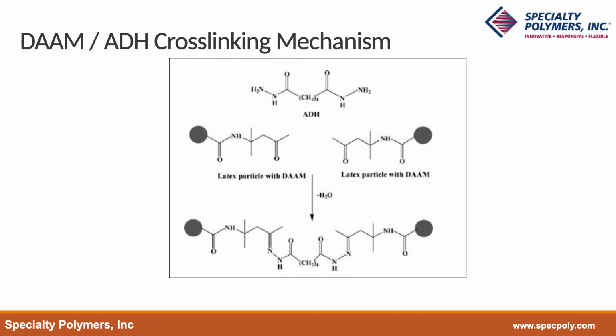These are 1K systems. The components are very stable in the wet paint and only react once the water leaves the film. You have the diacetone acrylamide attached to the polymer and the adipic dihydrazide in the water phase. The two molecules react by a condensation reaction of the amine on the pendant carbonyl and splitting off water. Because the water must come off for the reaction to go forward, the reaction does not occur in the wet state in the can, but only after the film has dried. This particular reaction is quite rapid.